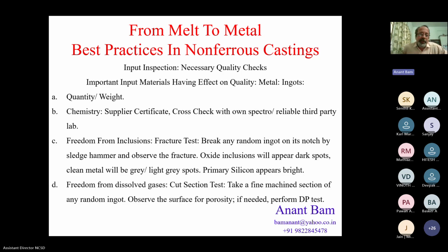Before unloading the truck, you should first verify the supplier certificate. Then cross-check with your own spectrometer, or if you don't have a spectrometer in-house, then cross-check with a reliable third-party lab. Take a random ingot. Every ingot has to be identified. It has to have a heat code number punched or engraved or painted on it. And any one random ingot you can take and cut a corner piece for a spectro sample and check it. If you have an in-house spectrometer, it's very good. You can qualify the input quality very quickly.